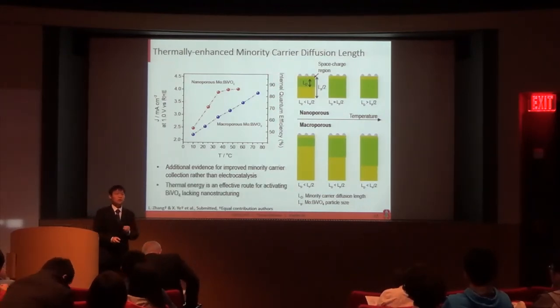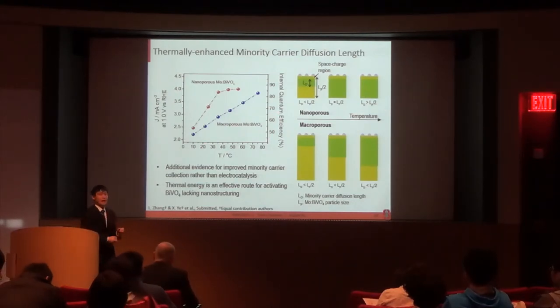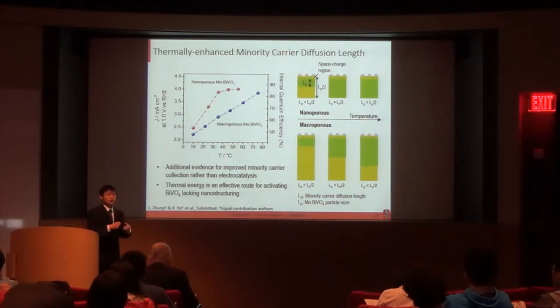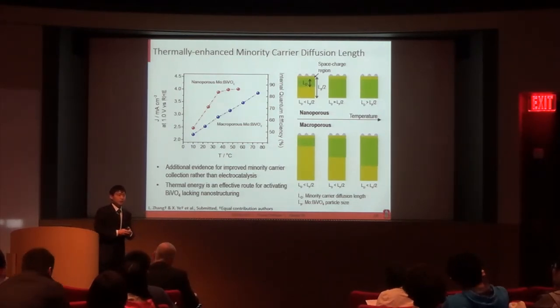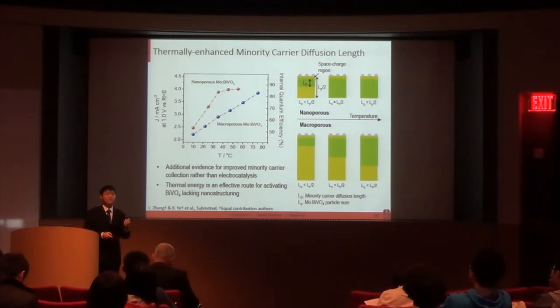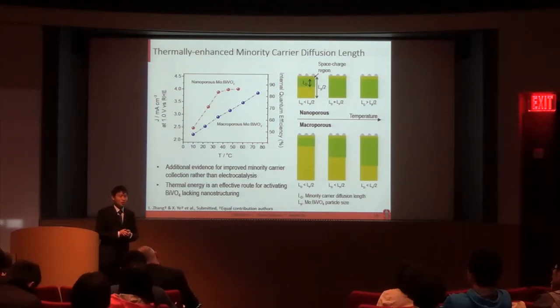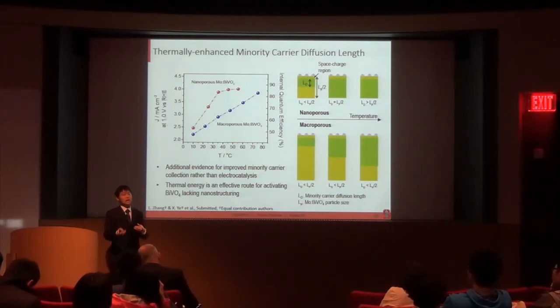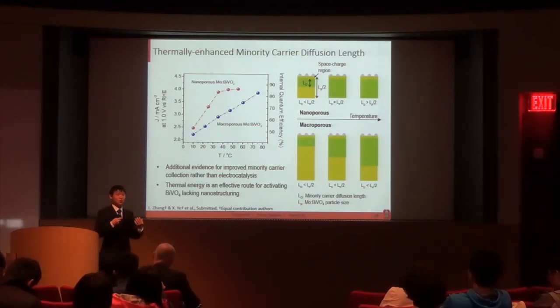Also, what should be noted is that the macroporous BVO actually can achieve any photocurrent level of the nanoporous BVO just by increasing temperature a little bit more. So that tells us thermal energy is an effective route to activating BVO without too much nanostructure. So we know nanostructure is a very good route for charge separation, but it also sometimes introduces more surface recombination or more degradation. So our result provides an alternative strategy to improve the photocurrent, but without extensive nanostructure.